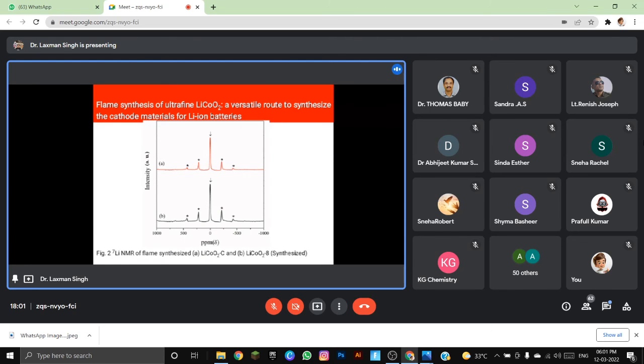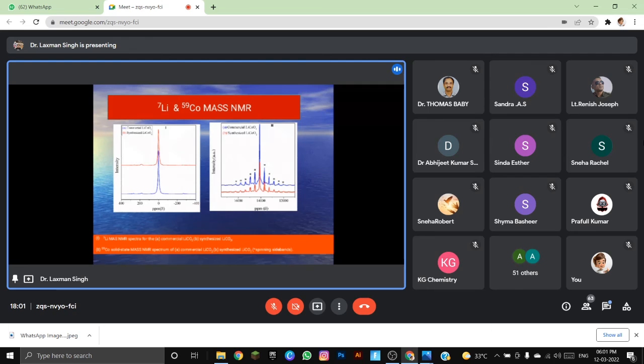And we have also used solid state NMR. In material science, solid state NMR is one of the best tools to determine structural stability at a molecular level, and it also provides the study of single phase material. Whenever we use the lithium-7 NMR, it shows that it is a pure material. It does not consist of any other secondary phase. We used the cobalt-59 MAS NMR also. These NMR analyses also show that this material is a single phase, pure phase material.